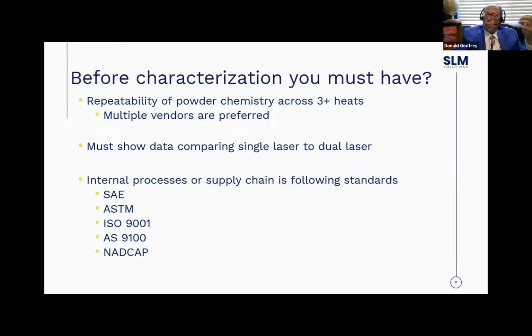So when we talk about powder, one of the things you want to know is whether your source of powder is consistent, and you typically look across 3 or 4 heats. What's best is if you use multiple vendors, but the key here is, let's say you buy powder from, I'll pick a company, Praxair, right? One of the things you want to do is make sure that the chemistry and the morphology of the powder is consistent and repeatable, right? And you don't do that by looking at their material data sheet. You send it out to a lab like Element or Westmoreland or whomever, and you have the chemistry and the morphology checked. And what you're looking for is repeatability.